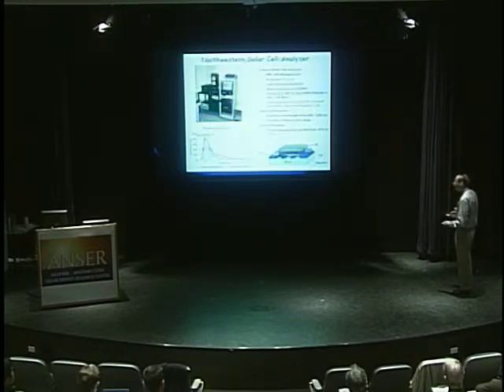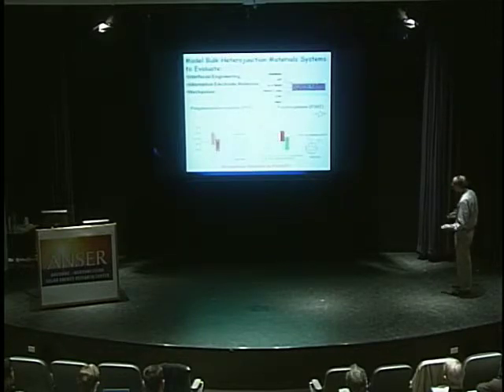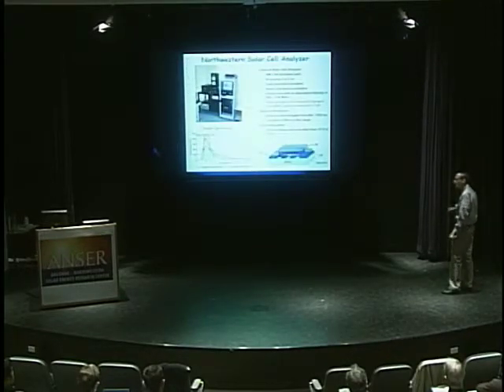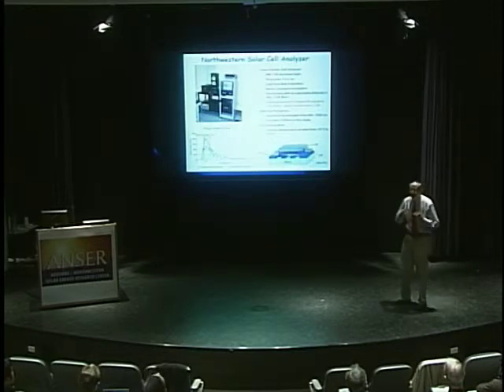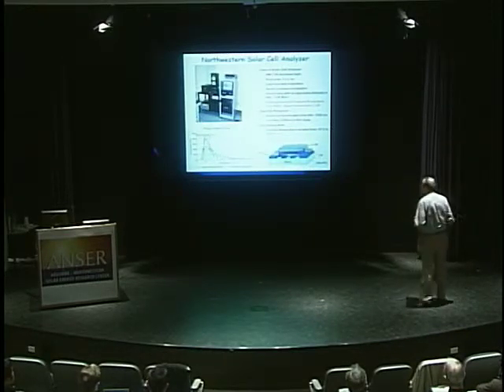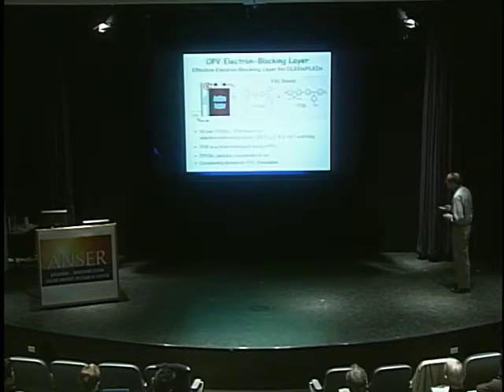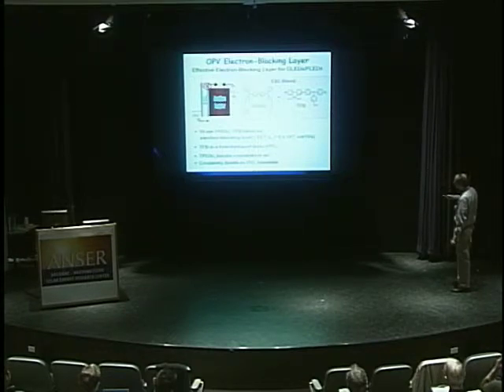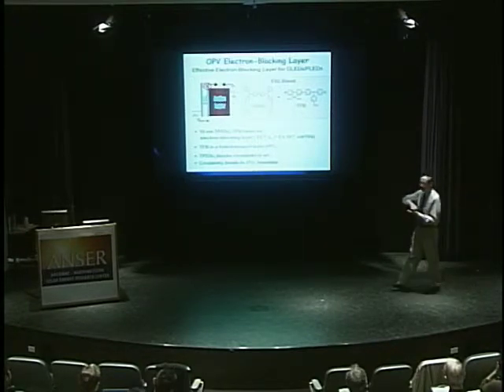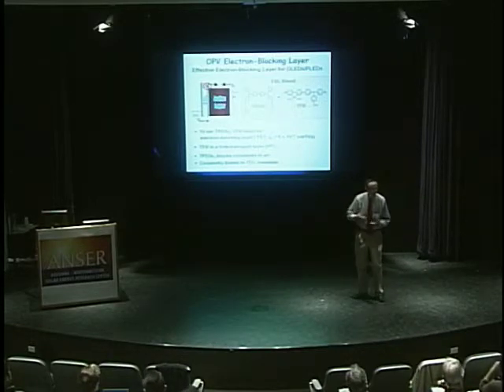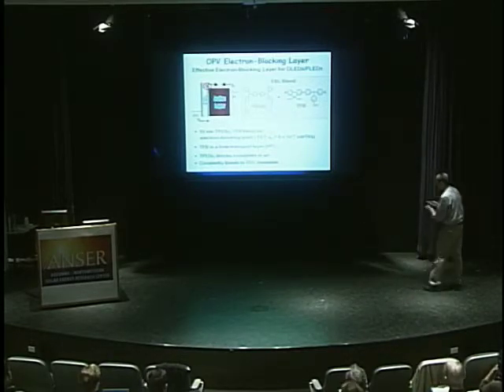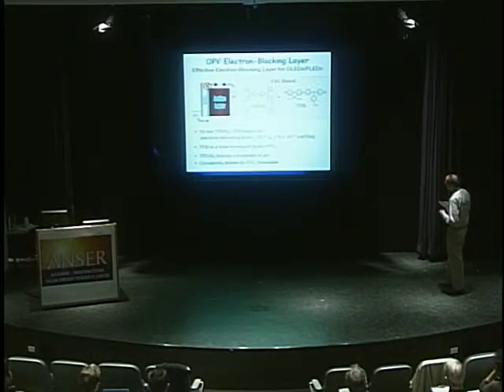And of course, as René already pointed out, neither of these materials is terribly good for capturing a large swath of the solar spectrum, but they're good materials to test some of our ideas about interfaces. So the first experiment we're going to use then, is take this TPD Si2, this blend. And remember I said we can spin coat this, it cross-links in air, we do a gentle anneal, and it's ready to go. And we're going to use about 10 nanometers of it, and it's got a mobility, as I said, about 10 to the minus 3, 10 to the minus 4. This is the hole mobility. It cross-links in air. It's very, very insoluble.